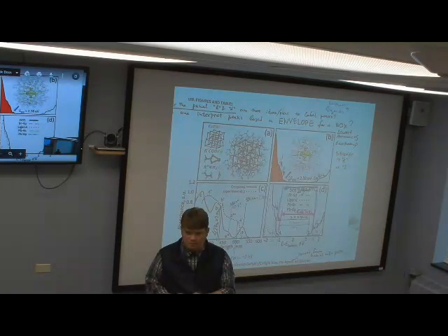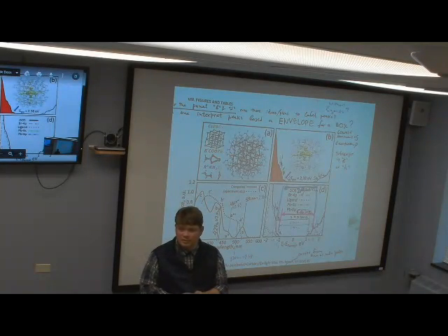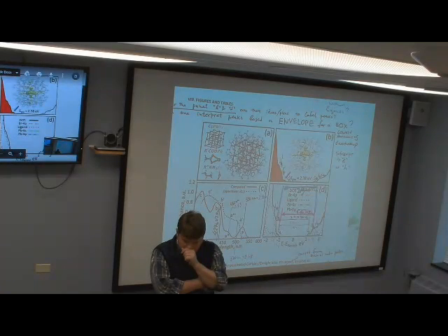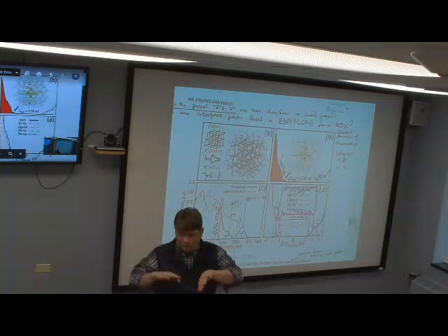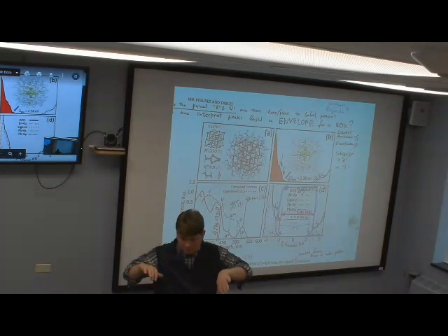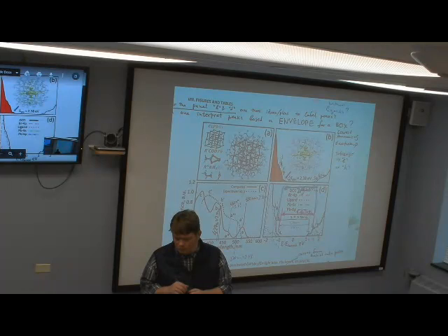By analogy to this SPD, one can also look at the one-dimensional box, seeing whether it is the lowest available state. Again, we have two progressions, one for electrons and another for holes. Instead of S, it is just the lowest state. Instead of P, it means it is an excitation either in X, Y, or Z direction with one node. D will be either two excitations in different directions or a double excitation in one direction.